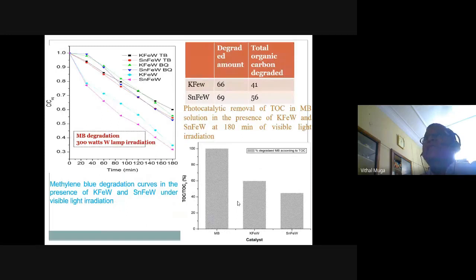Now you see in the next diagram that the tin doped compound has shown the highest activity. This is methylene blue, an organic dye pollutant, used as a model pollutant. Now C by C0 at equilibrium. Always we measure, and if C by C0 is 1, that means initial concentration only. As the time of irradiation passes, you will see that about 70% is decomposed. This is significant. So methylene blue degradation occurs under visible light irradiation.